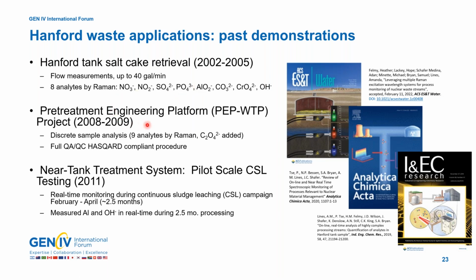In the late 2000s, we had another application where we supported the pre-treatment engineering platform, or the PEP platform, for the waste treatment plant, where we again had a Raman system where we could measure 9 analytes from grab samples that were taken from the PEP plant and sent to our laboratory. We could analyze the 9 analytes. It was these 8 up here that I've mentioned before, plus oxalate. And this was a fully QA/QC HASQARD compliant procedure that we developed with a Raman probe. So we could measure these and have the analysis back to the PEP plant within a 24-hour period. And so this was really good. We supported that plant for about a year while they were running that design plan.